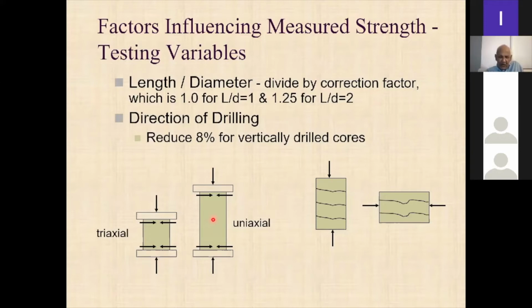Anyway, because in our case we are converting to equivalent cube strength, like I said, we typically use length upon diameter ratios slightly in excess of unity, right? There are ways to convert that in order to get the equivalent cube strength, right? Now, also the direction of drilling is important, right? Now, this would be if it is a vertically drilled specimen. Now, if it is a vertically drilled specimen and this is a horizontally drilled specimen, if you think about a column, right? Now, the concrete is poured into the column like this, right?